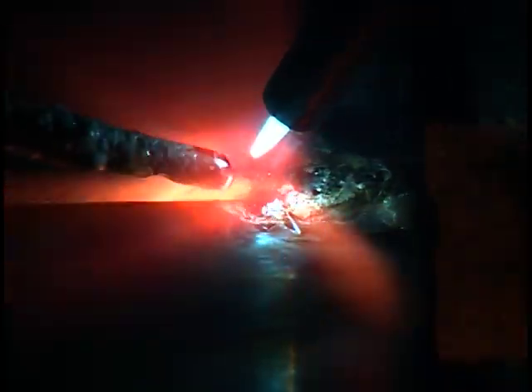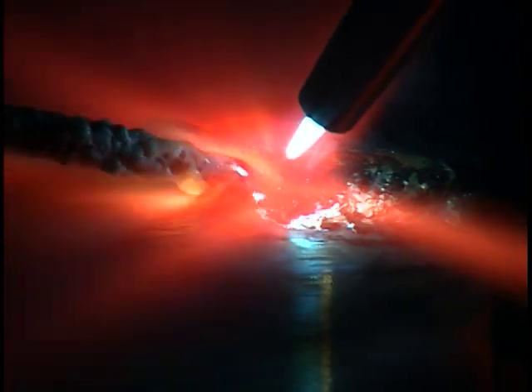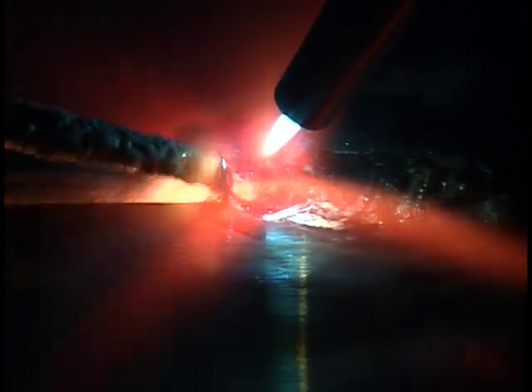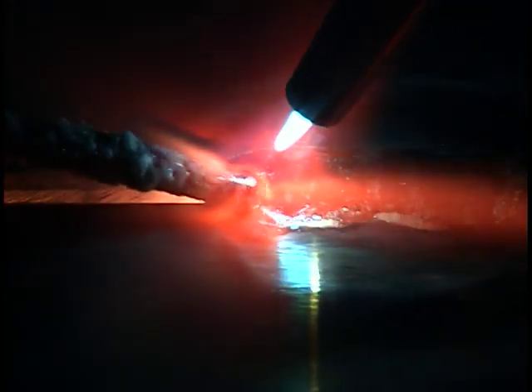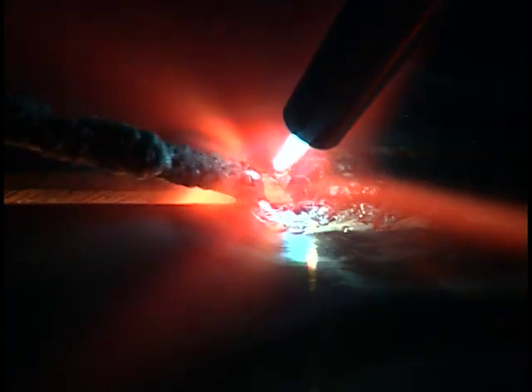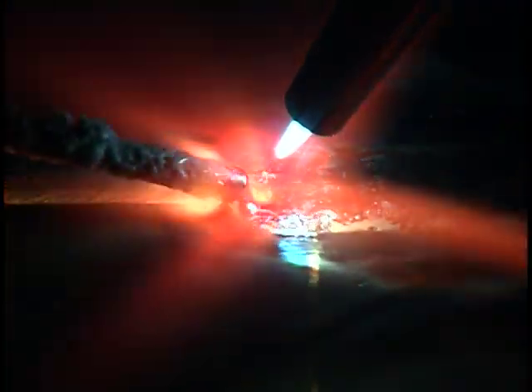Hold the torch in position, and when the metal becomes dull red in color and the flux is liquid, dip the rod into the edge of the joint and deposit some filler metal. Do not melt the base metal. The filler should flow into the joint opening and spread out slightly where there is flux. This spreading of the filler metal is referred to as wetting or wetting out.